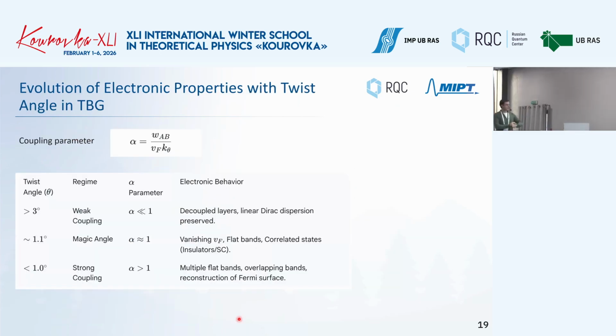Here are a few words regarding this coupling parameter and the different regimes depending on the angle. So you change the angle and you have the different regimes: so-called weak coupling, magic angle, and strong coupling. When it's weak coupling, as I mentioned, there are decoupled layers, but at the magic angle you can obtain another electronic behavior, and you expect to see correlated states and flat bands. And this is exactly what people demonstrated when they observed superconductor and Mott insulator states in this regime.